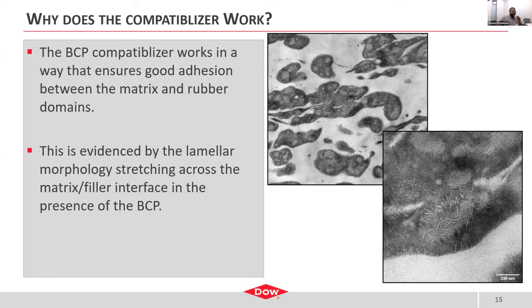This is with the block copolymer compatibilizer that is in there. The reason you have this contrast is again because of the heavy metal staining that is done. If you expose a TPO-like material to ruthenium tetroxide, the polyethylene domains will take up a lot of the ruthenium and allow you to have a lot of contrast in transmission electron microscopy.